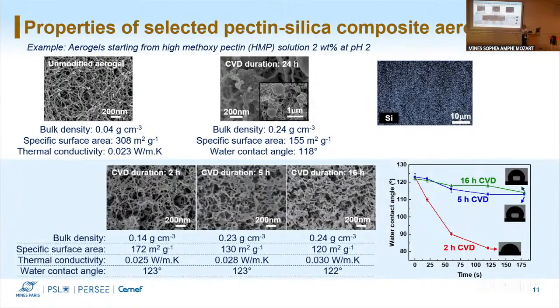Yes. So the idea for this was to see if the hydrophobization is all the way through the material. And pectin aerogels, when you have a disc, to remove parts of the disc, it's not easy to cut it with something. We tried with different things. We didn't manage well. So we thought that the best thing is to polish to get a flat surface. And I can see for materials that I know are homogeneous, not needing pectin, that when I polish the surface, I have an increase in contact angle.